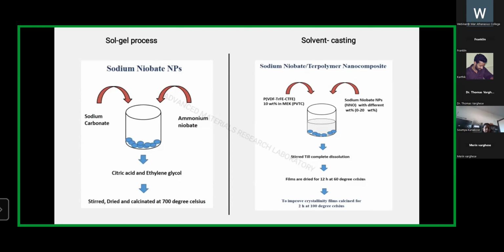And terpolymer nanocomposite films are prepared by the solvent casting method. For that, the polymer part is fixed and the sodium niobate part is varied. After complete dissolution, films are cast in a petri dish and dried at 60 degrees Celsius. And to improve crystallinity, it is again heated at 100 degrees Celsius for 2 hours.